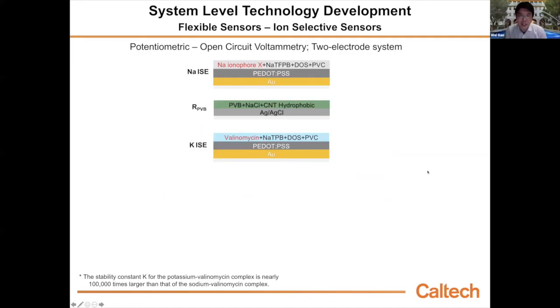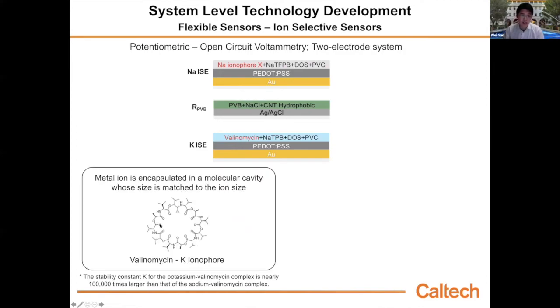To monitor ions such as sodium, potassium, hydrogen ion, basically pH, or calcium, magnesium, for example, we could use ion selective electrodes. In this case, we modify our working electrodes with an ion selective film. This film is selective to the given ion. For potassium ion, for example, it contains a specific ionophore, valinomycin, where the size of this ring, this molecular structure, is matched to the potassium ion.